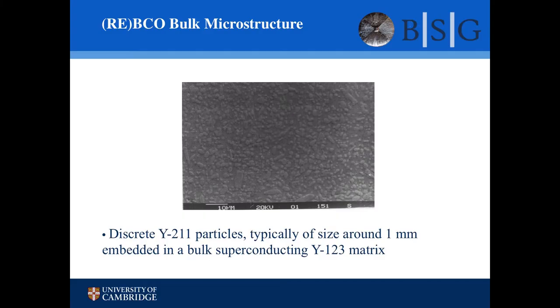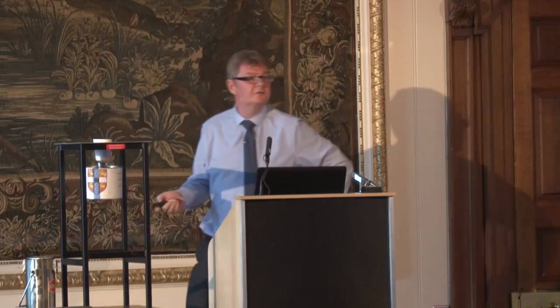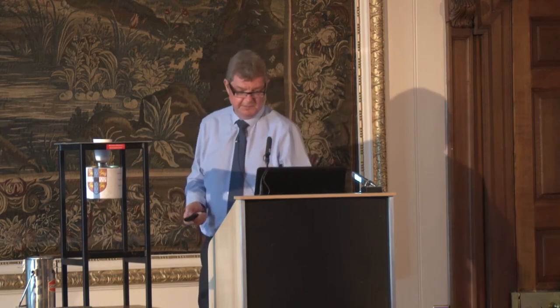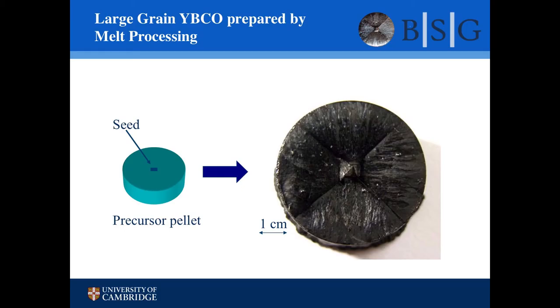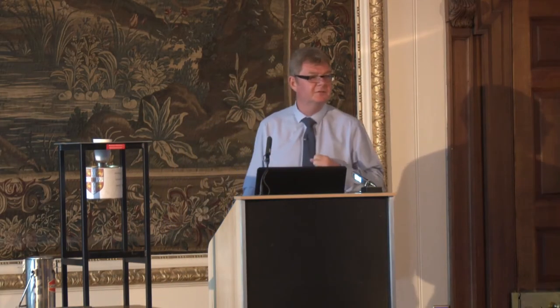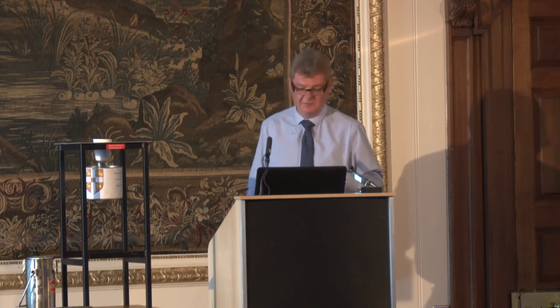If you look at the microstructure, I don't know if you can see, but there are these discrete second phase inclusions. And between them, we've got this continuous superconducting phase. And these second phase inclusions are going to be very good for flux pinning. If you get it right, this is the kind of sample you make. So these are things of beauty. I'm amazed that they haven't found a market in jewellery. But every time I see one of these very spectacular large single grains, the elegance of the process isn't lost on me. The record size is 13 centimetres, Nippon Steel, single grain 13 centimetres diameter.